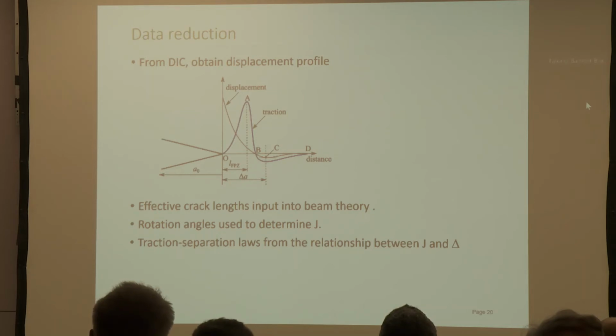But what we're able to do here is measure the displacement profile ahead of the macroscopic crack tip. And that's shown by the red line in the data. And of course, one thinks about the traction separation law additionally. And one of the things that we wanted to do is to define as accurately as we can the effective crack length. As I mentioned earlier, the effective crack lengths have an advantage. And if we can come up with routines for automating their measurement, then we can implement those effectively in the analysis solutions.